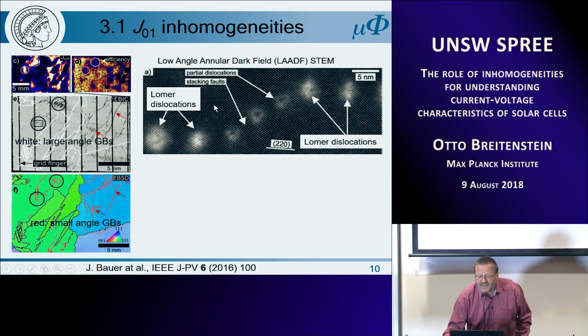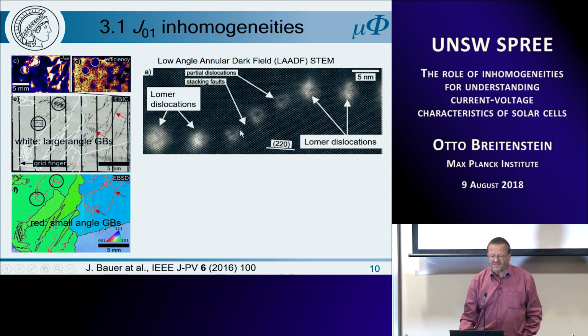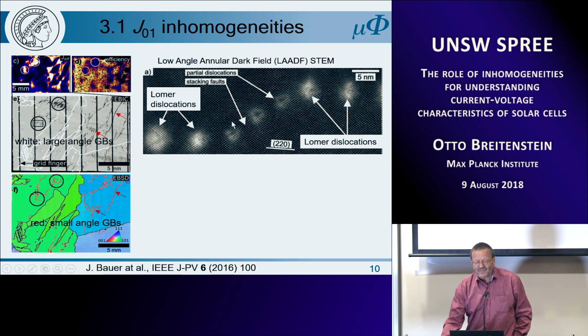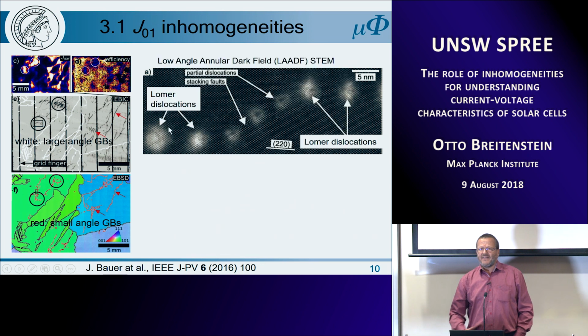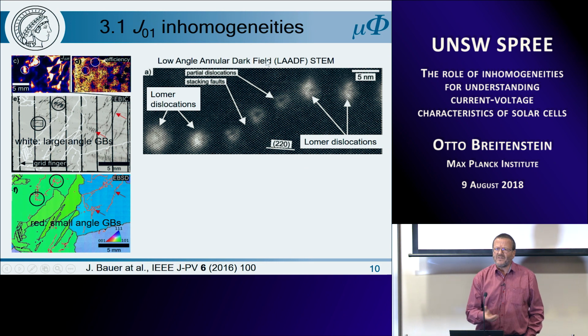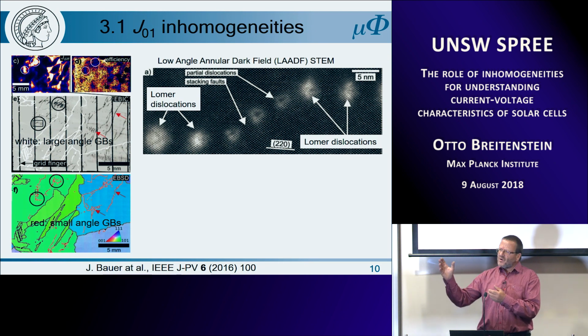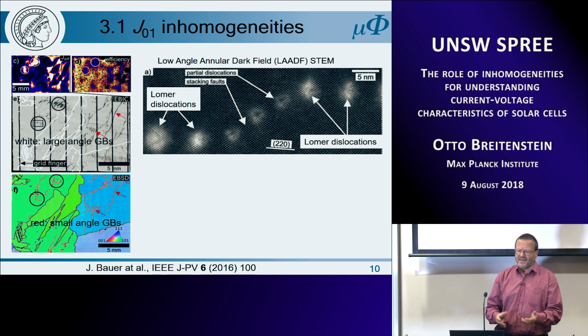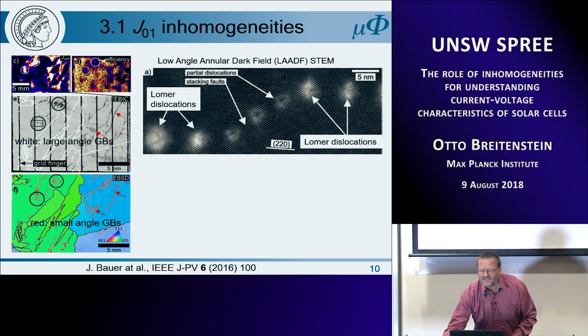And here, for example, you see that is stacking faults. So if these atom rows make a kink, then this is a stacking fault. And if you have regions of internal stress, they show up as bright regions, like here. I have to explain: most of the grown-in dislocations in solar cells are split into partials. They do this in the process of cooling because of minimizing their energy. And then they have these stacking faults in between. But some of these dislocations are unsplit.